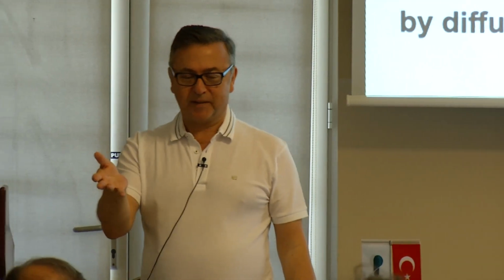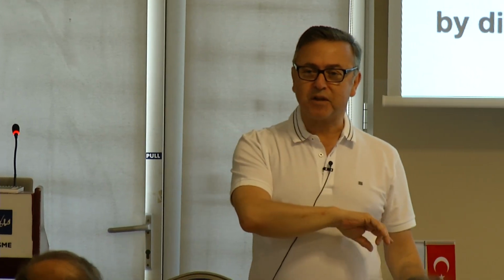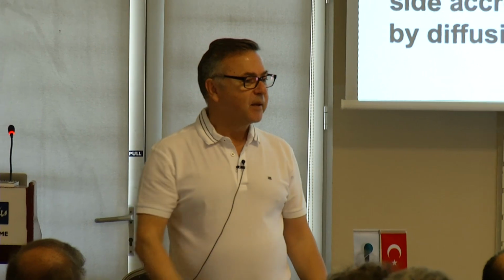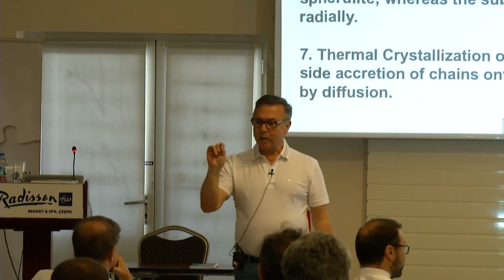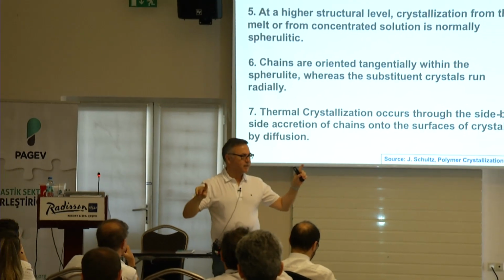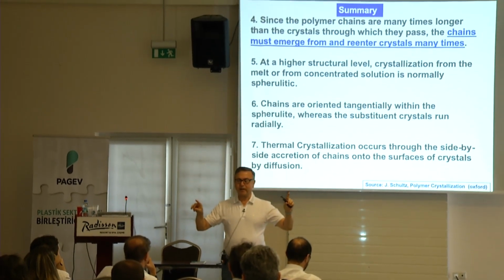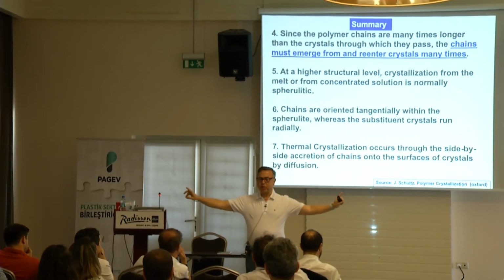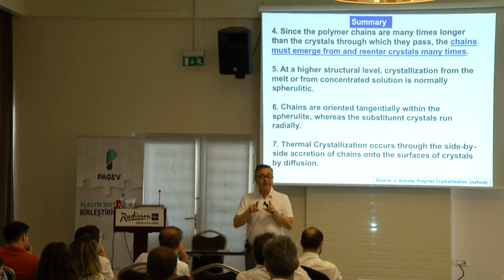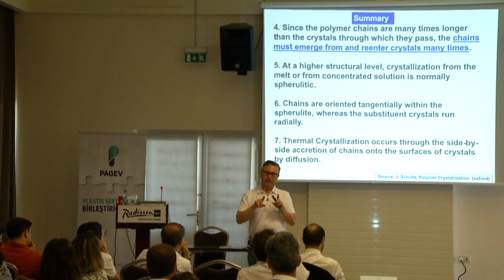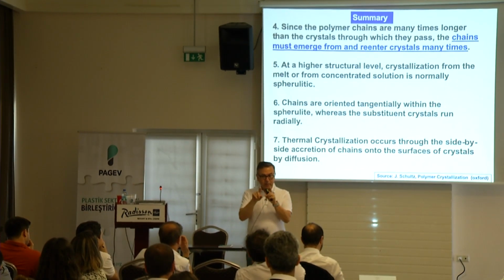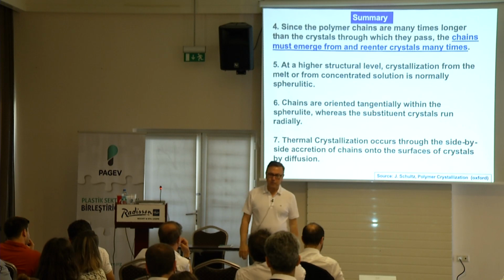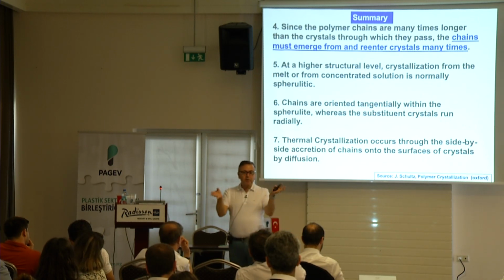Viscosity, diffusion, related. So how do you control the viscosity? Temperature. What else? Pressure, yes. What else? Concentration, exactly. What else? Long chain molecule versus short chain. Long chains cannot diffuse as fast as short chains. Right? So short chains can diffuse faster under the same conditions than long chains. So you got it. So you know how to control all of this.